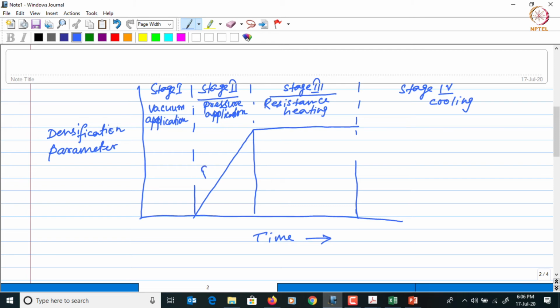So pressure is increased continuously and the compact is then held at a particular pressure as the sintering temperature is reached. And as the heating takes place, the temperature increases continuously, all the way to the sintering temperature. And once the sintering is accomplished, it is cooled down. Right, so these are the 4 stages of the SPS sintering process.